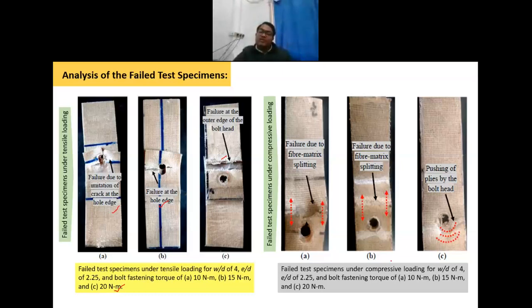But in the case of compression, you can see under compression testing the specimen fails in a different way. There is fiber matrix splitting or pushing of the plies by the bolt head. So different modes of failure we have observed under tensile and compression loading. So this is one technique that we have applied, mechanical joining.